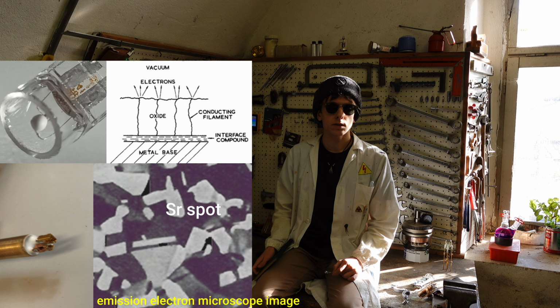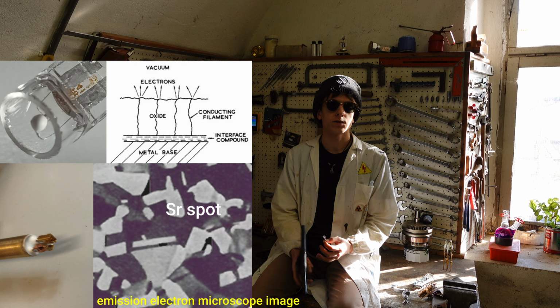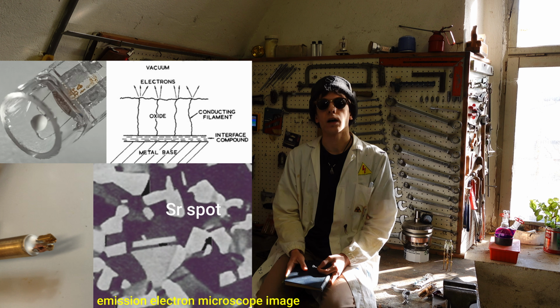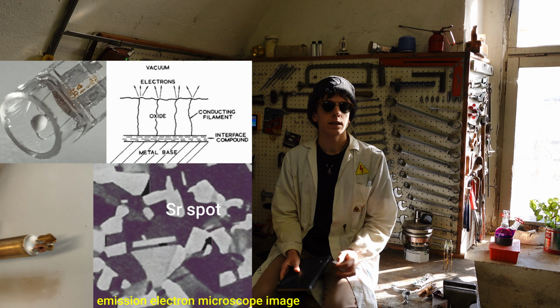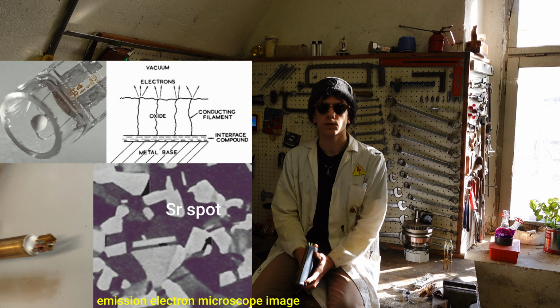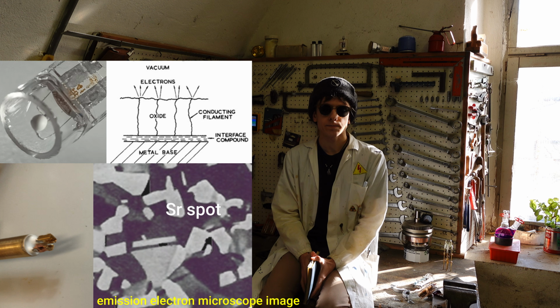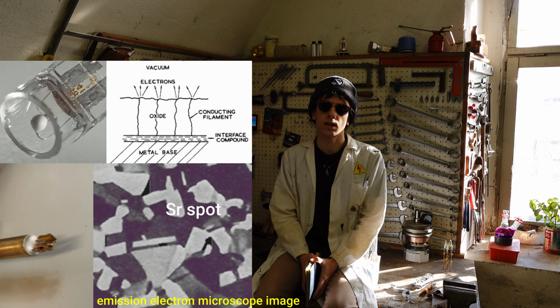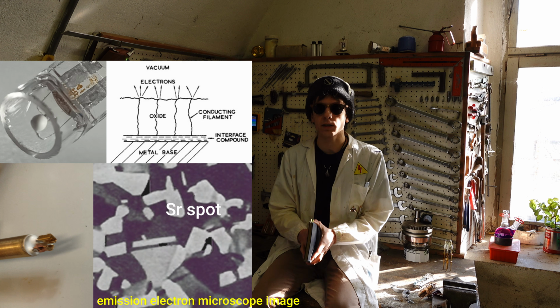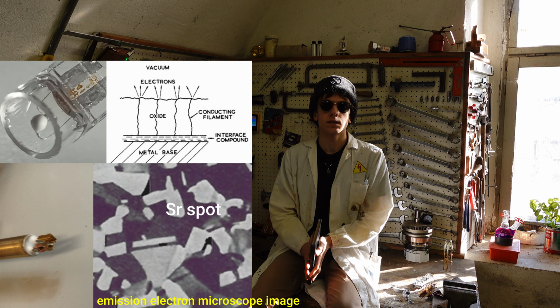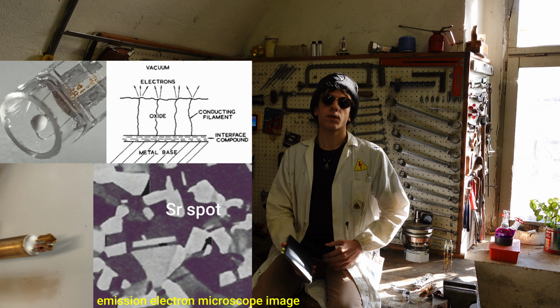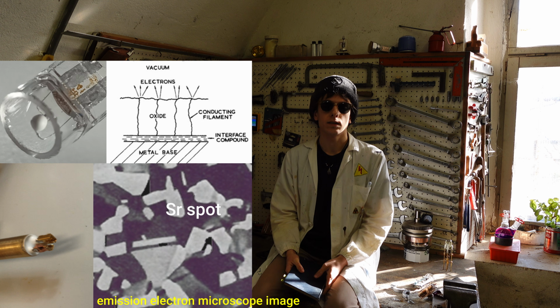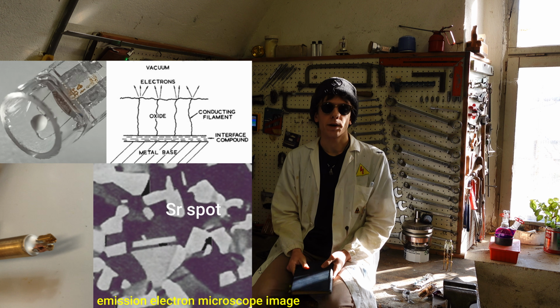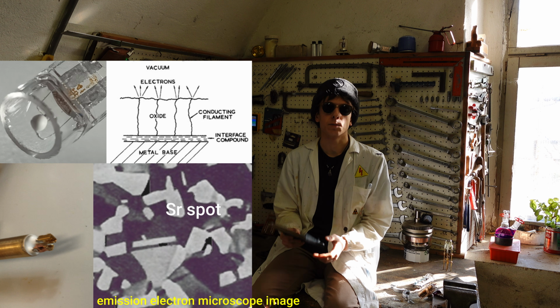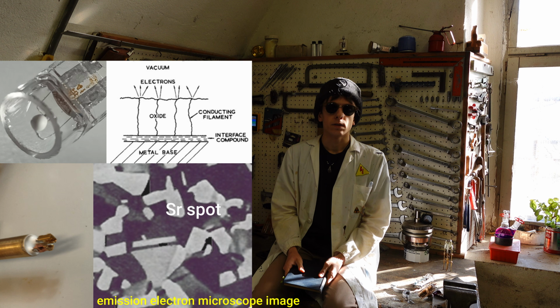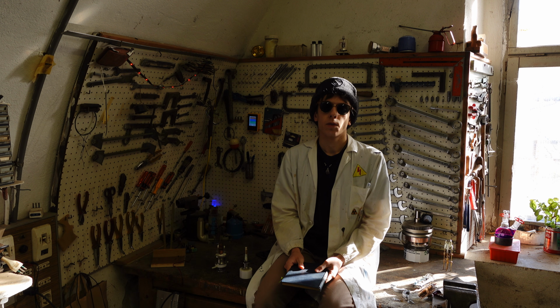During the activation process, inside of the oxide layer some channels are created that allow for ionic conductivity to kick in and enable the escape of the electrons from the surface where they are created. This process is extremely sensitive to poisoning from gas present inside of the chamber, and this is the reason why on amateur level this type of cathode cannot be easily achieved, at least in a dynamic system like mine, where I want to open and close the chamber often, because even after the slightest contact with air, the cathode needs to be reactivated.